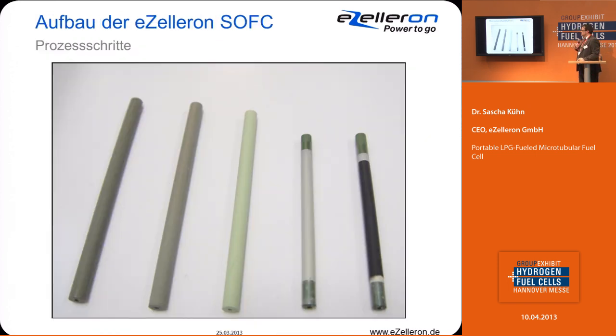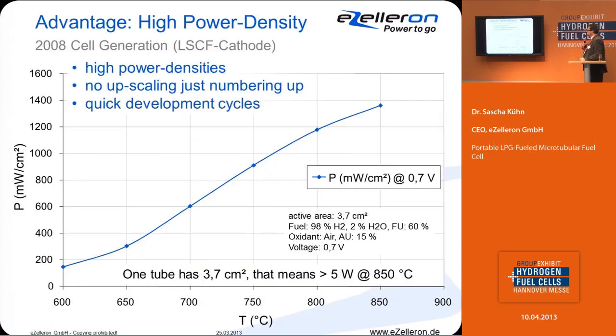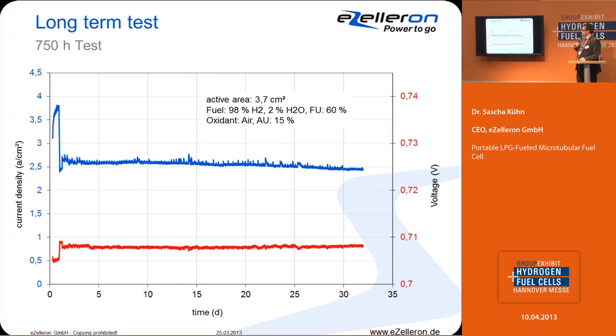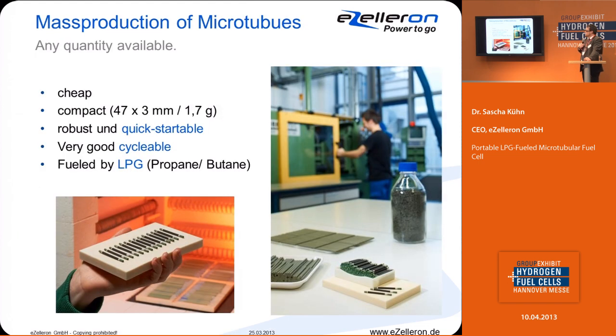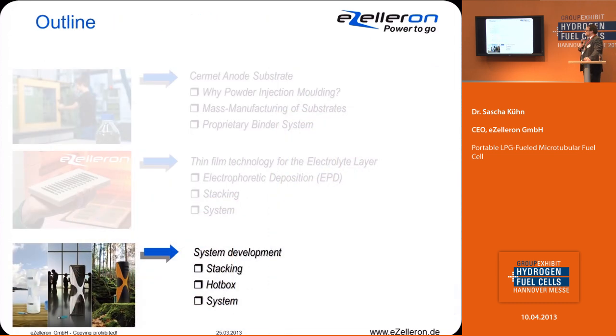This shows the different steps of manufacturing again. And the advantage of these tubes is that they have a very, very high power density. They are not developed by scaling up processes, but we do a numbering up. And that means we have very quick development cycles. The long-term behavior is also quite good because we're heading for the mobile markets. 3,000 hours is the benchmark, and we have only a slight degradation in our 750 hours tests. Mass production of the microtubes is possible.